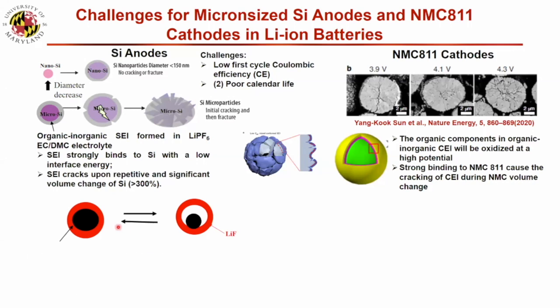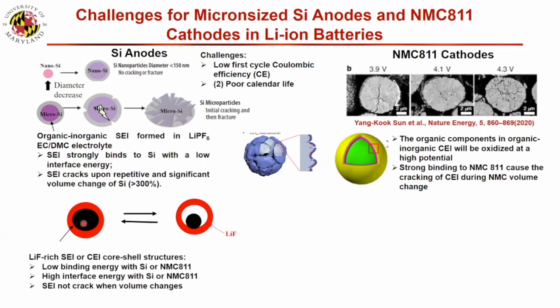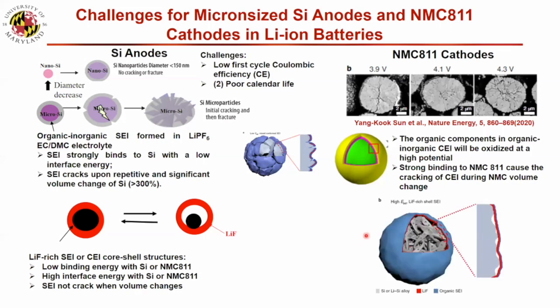So our design idea is this: this is the active material, whether silicon or NMC811. If we can form lithium fluoride, which has a high interface energy, the bond is so weak. When the volume changes, the particle shrinks and expands, and because the bonding is so weak, the SEI is stable; lithium fluoride is stable. So we hope that in this case electrolyte cannot penetrate. So even if they crack, they still make contact and keep working. We assume that if we have an SEI, a lithium fluoride SEI on the surface, even inside the crack, it should keep a stable cycle life.